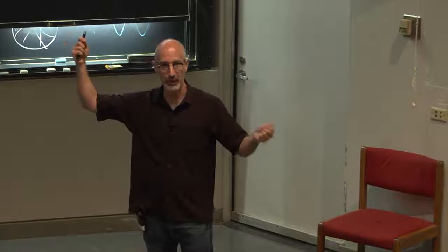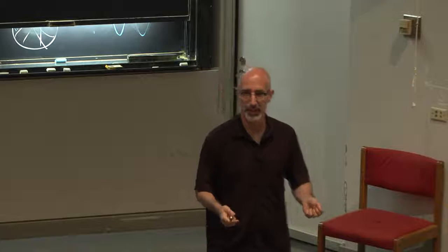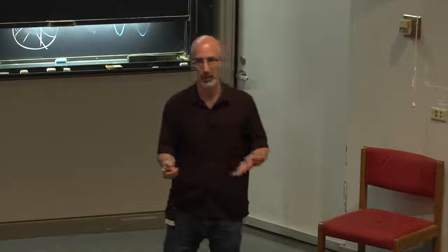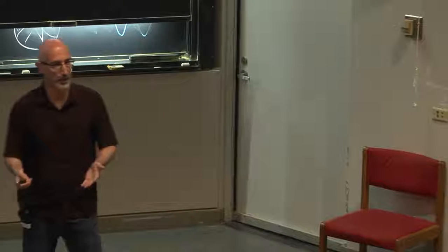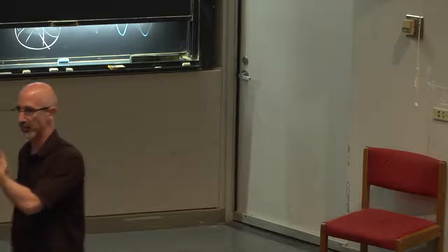Okay? If that was the fundamental length scale in the system, then you would expect large finite size effects in your computer simulations. Right? If you simulated 200 particles, you would expect the answer to be different than if you simulated 1,000 particles. But there's no difference. Actually, finite size effects in simulations of most models of supercooled liquids are extremely small. So it argues, at least in my mind, that the length scale that's important is not fundamentally the distance between the defects.